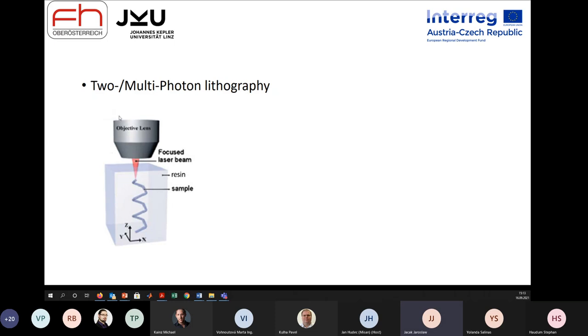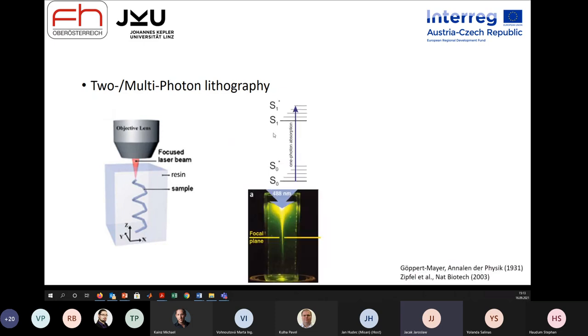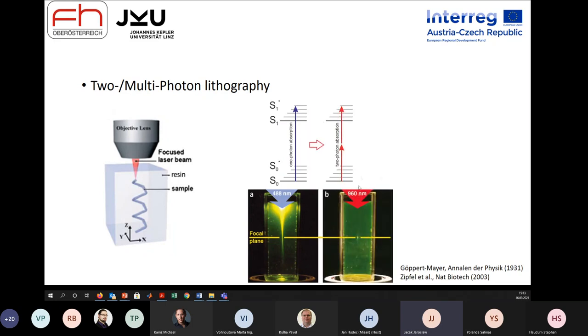And the idea of multi-photon lithography is more or less simple. You use a femtosecond pulsed laser. You focus into a resin, and in the focus of the resin, you get sufficient intensity in order to cross-link your polymer. Of course, it's a radical polymerization. You need photoinitiators, and basically by moving your objective, you are enabled to print 3D structures. And we typically use not stereolithography with 1 photon absorption, but 2 photon absorption.